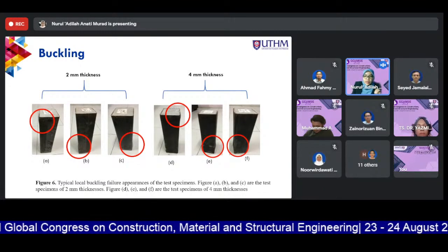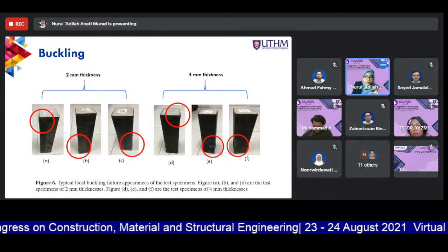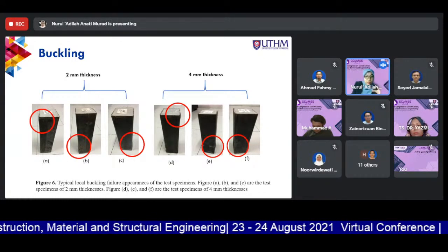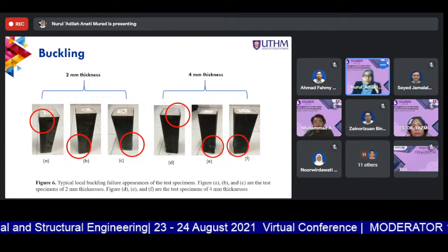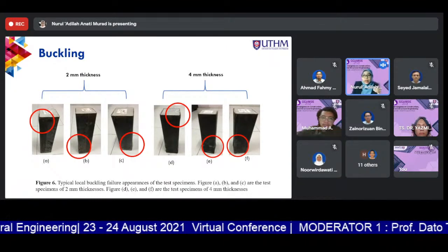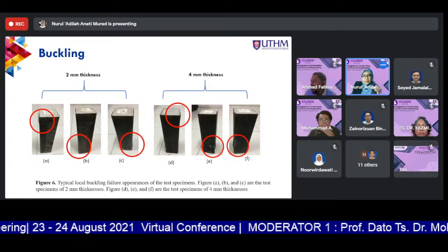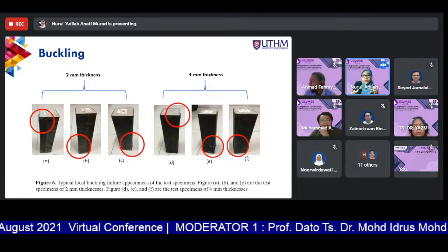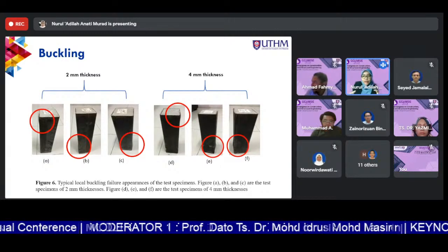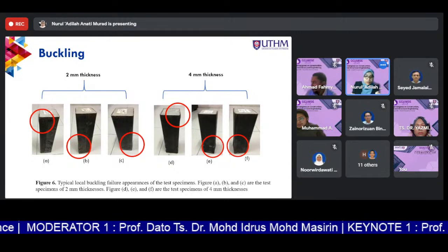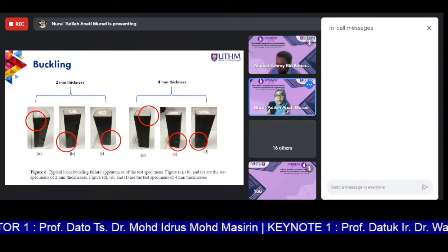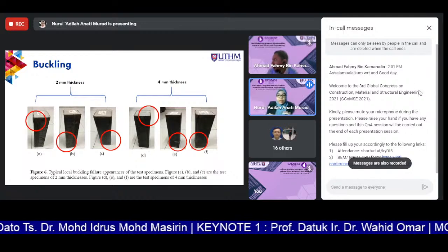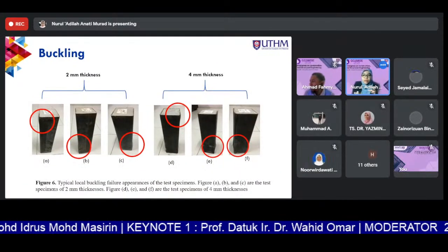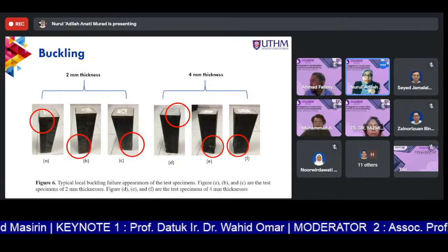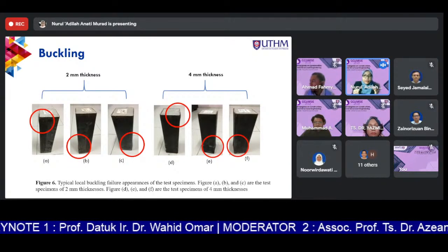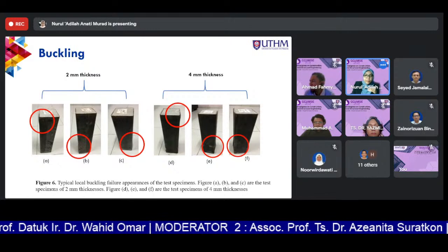Okay, and this figure indicates that the local buckling mode on the steel hollow section structure for 2 millimeter thickness is more significant than the 4 millimeter thickness. And the buckling mode on these specimens is also non-consistent. And this appearance can be related to the bonding strength between the steel and the concrete, and by referring to the surface irregularity, such as roughness of the steel section or surface of the concrete cross-section, along with the specimen size and its effect on the bond strength.